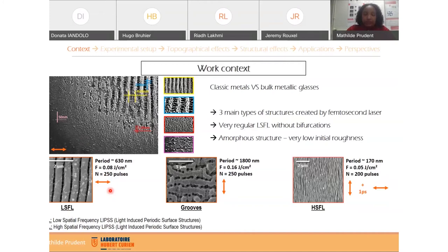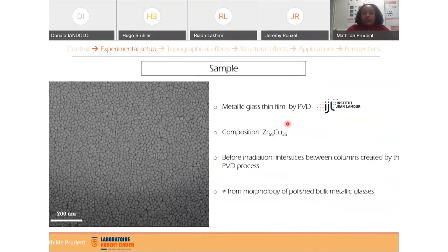At the beginning of my PhD, we did some preliminary work about the interaction between femtosecond lasers and bulk metallic glasses, and we brought to light the possibility to create three main types of structures after irradiation. So here LSFL, very regular LSFL, grooves, and also HSFL. Now we will discuss the interaction between femtosecond laser and metallic glasses in the thin film shape. For this, we use a metallic glass thin film manufactured by PVD at Institut Jean Lamour in Nancy. And the composition of this thin film was 65% of zirconium and 35% of copper.